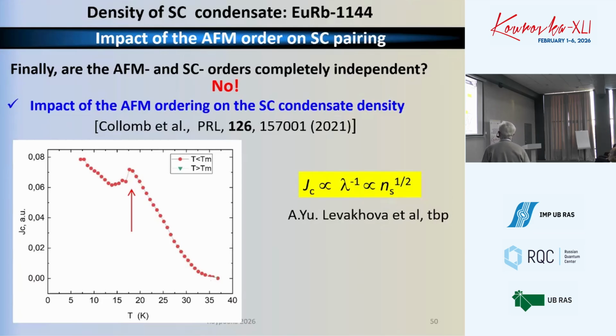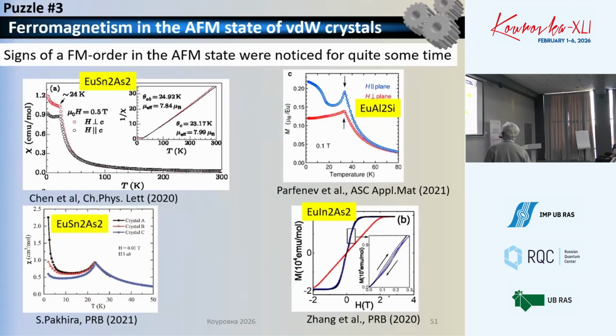Now I want to move further to the simple non-superconducting material, which is europium tin arsenic, to show that despite this being a very simple non-superconducting semi-metal, it has several remarkable features. When you look at the literature and find numerous papers, you notice that the behavior of the spin susceptibility is quite wonderful. You see that when temperature approaches 0, the susceptibility, instead of saturation, tends to diverge.